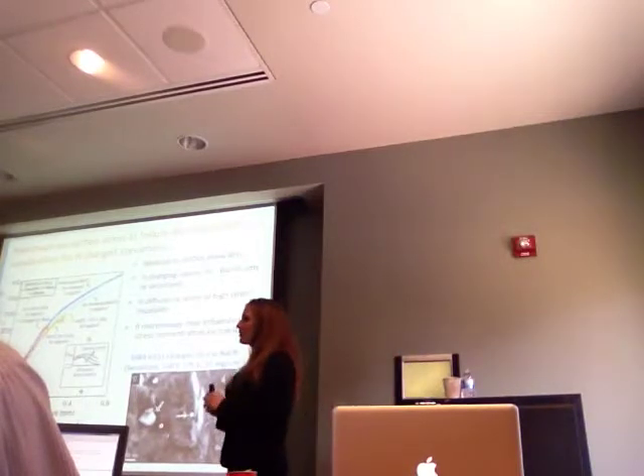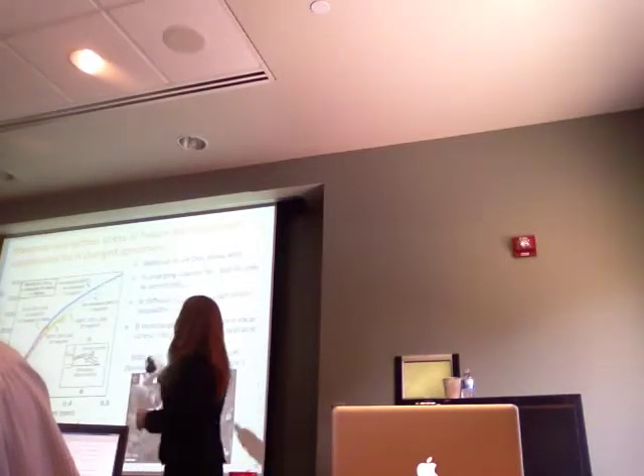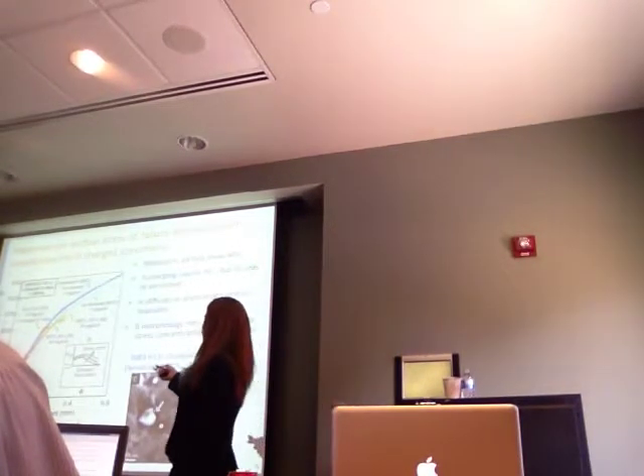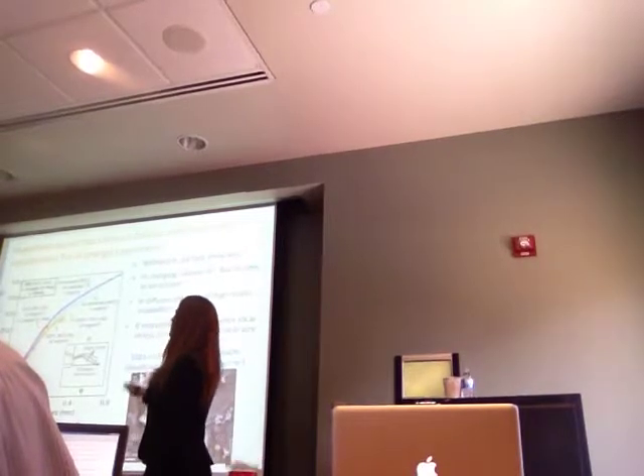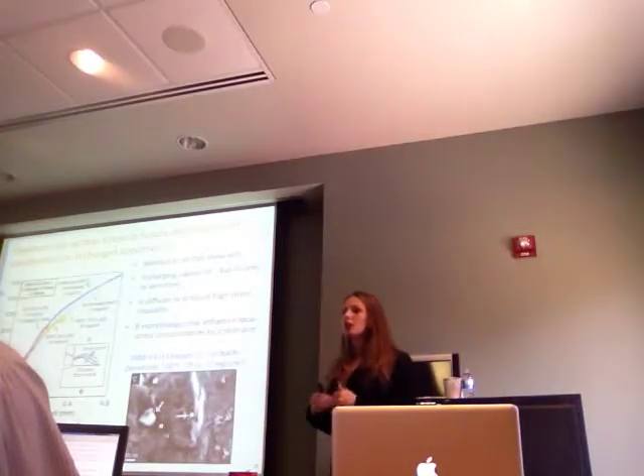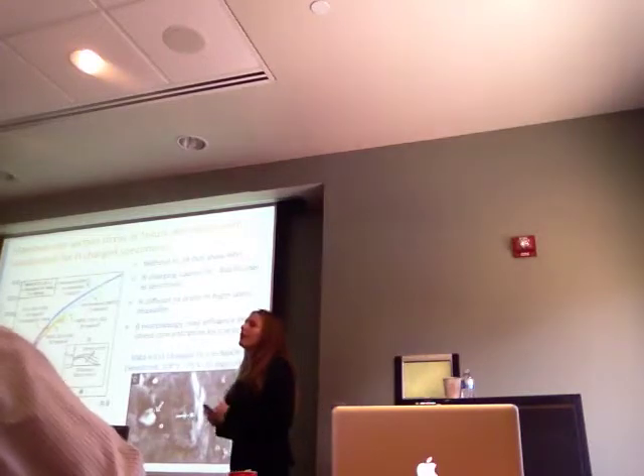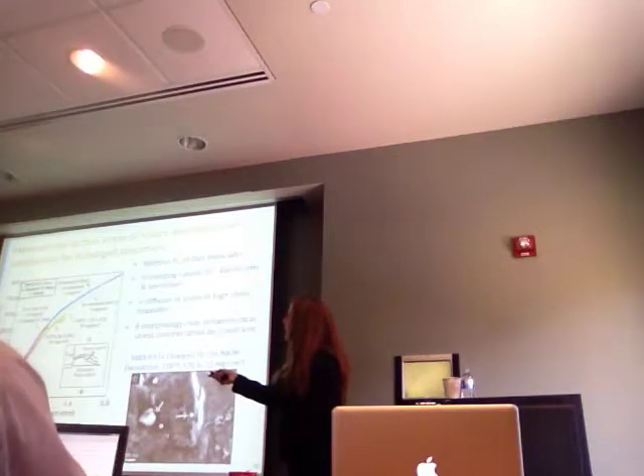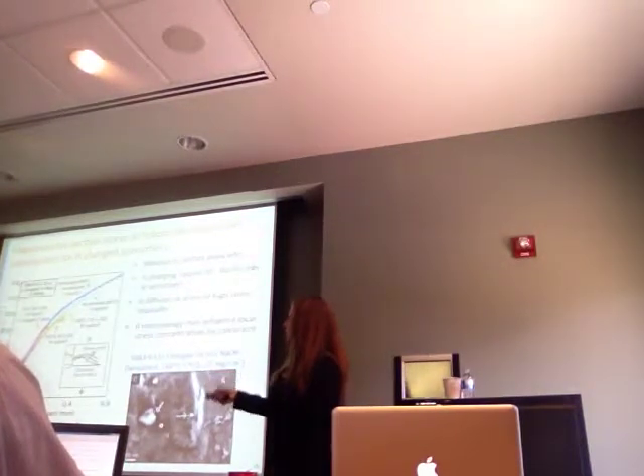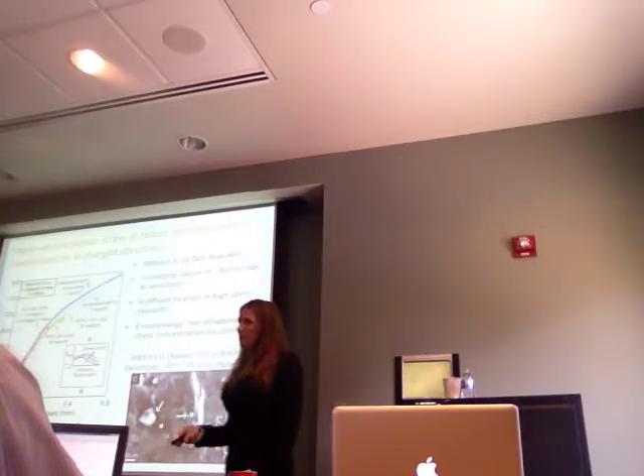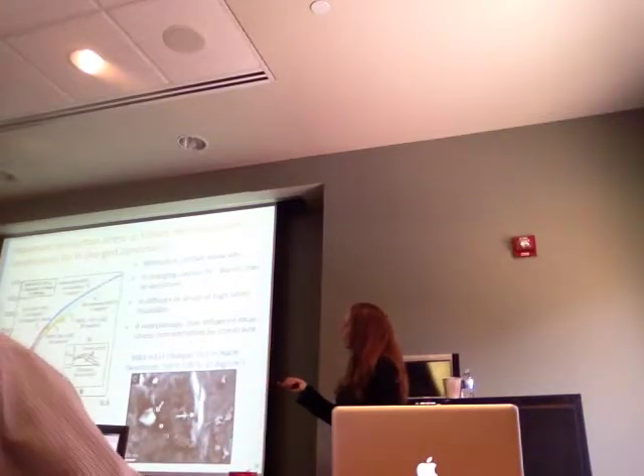The blue line up here is an uncharged as-received beta-free specimen. And you can see that it broke at a very high stress. When we charged this as-received specimen here, you can see that the stress that it broke at was much lower. So we are in fact embrittling this microstructure just by putting hydrogen in the microstructure. Then when we charge the sensitized specimens, which are these three here, at 22, 50, and 23 milliamps per square centimeter, our stress at fracture is even lower.